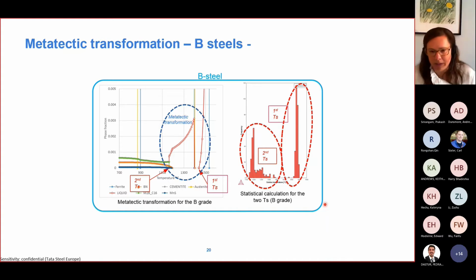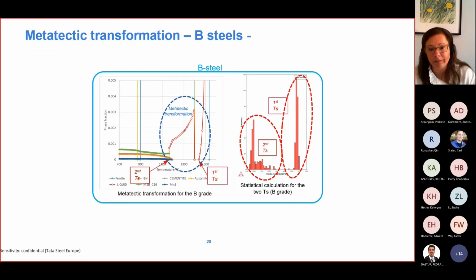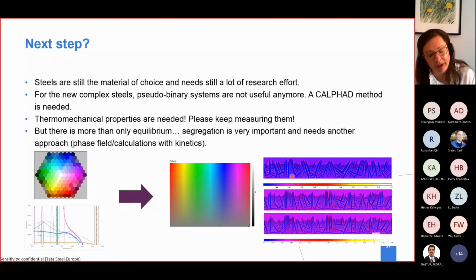Luckily, a lot has been studied, not only by us but also in the world. There are lots of publications about this metatectic transformation in steels alloyed with boron. Here, nicely enough, Thermo-Calc, or a thermodynamic diagram, shows us the different liquidus and solidus temperatures, because you will have two liquidus and two solidus temperatures in this case. You have the first one and the second one. I'm just plotting solidus temperatures, but you have two of them. You have to be aware of that as well.